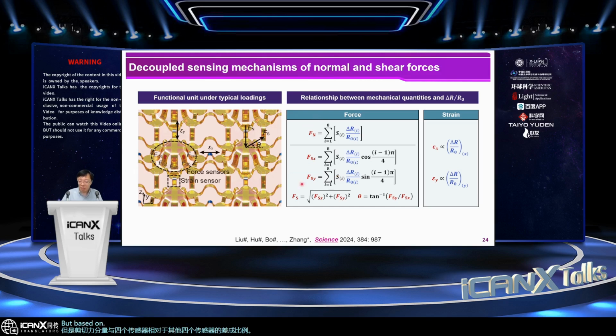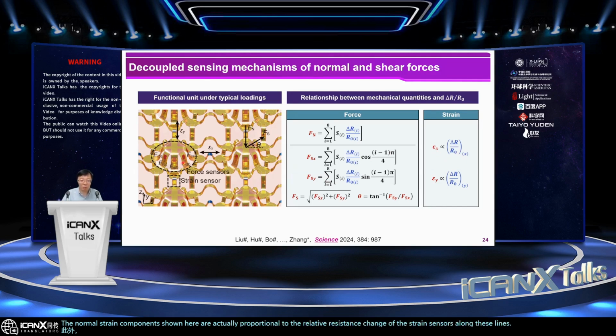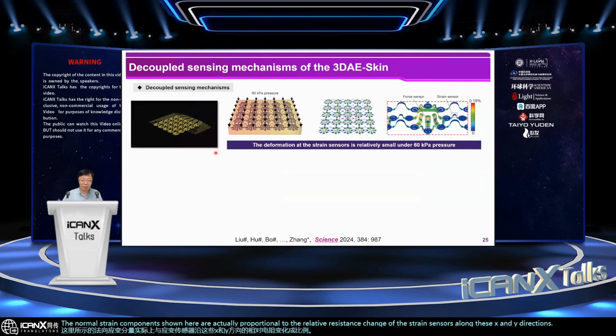Based on these equations, we can measure both the normal force and shear force components directly. This is also owing to the 3D cage mesostructure. Additionally, the normal strain components shown here are actually proportional to the relative resistance change of the strain sensors along these X and Y directions.